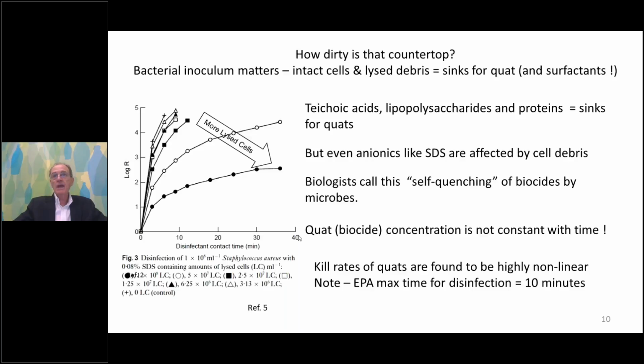And the EPA, who regulates disinfecting products, is not going to give us 30 or 40 minutes to achieve disinfection. We have a maximum time of 10 minutes that we need to do our job in. And they tell us also that we need to have, depending on the organism, 3 to 5 log reduction. So the kill kinetics matter a lot, and dealing with self-quenching matters a lot when we're formulating a disinfecting product.